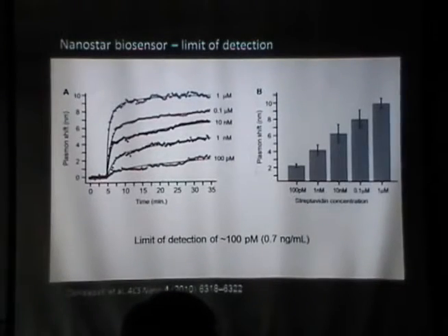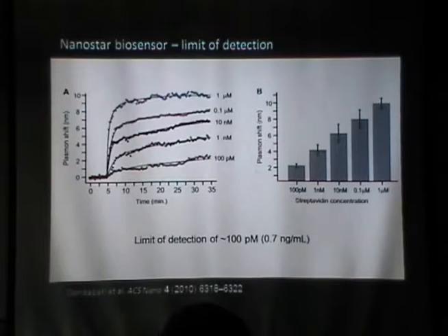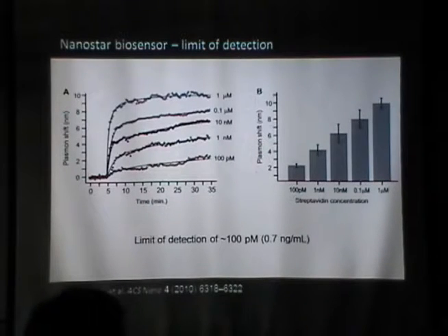Okay. Question. Are those nanostars made of gold? They are made of gold, yes. But to make them, you need to add, you know, these nanoparticles are all made by nucleation and growth methods. In this case, it turns out that you need to add a small amount of silver ions in the solution, and then they start to branch. But the amount of silver is negligible. It's like a catalytic effect. So they are mainly made of gold.